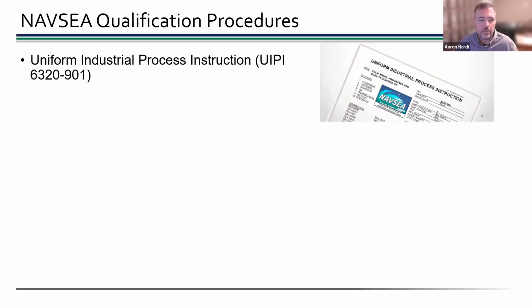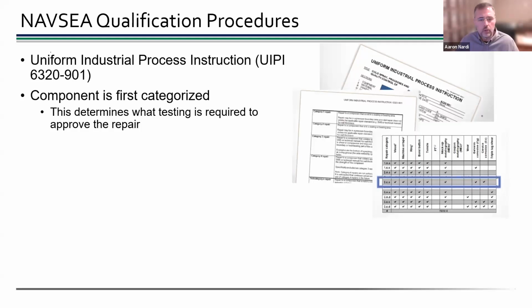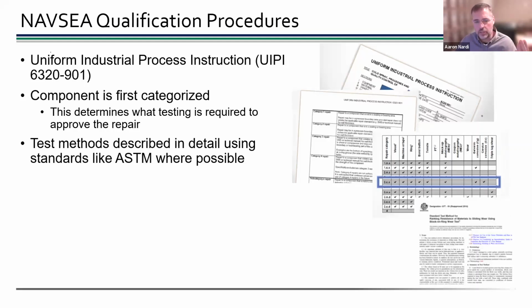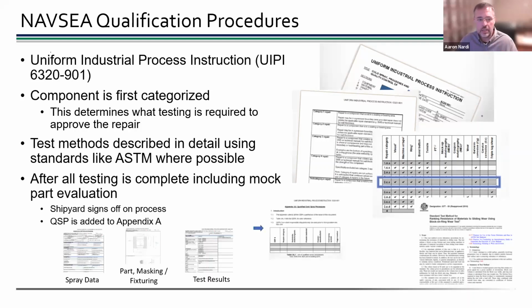This is kind of unique amongst the DoD because it has that cross-platform capability, I guess. So the way this works, like everybody else, you qualify what that category of part is, whether it's structural, wear, corrosion, whatever. You identify the tests you're going to do. You pull up the ASTM standards. You run it per the standard or per the UIPI itself, depending on the test you're running. And then when you're done, all that data goes back to the shipyard. They sign it off, and this QSP goes into the appendix of the QSP of the UIPI. So it's a pretty straightforward process.